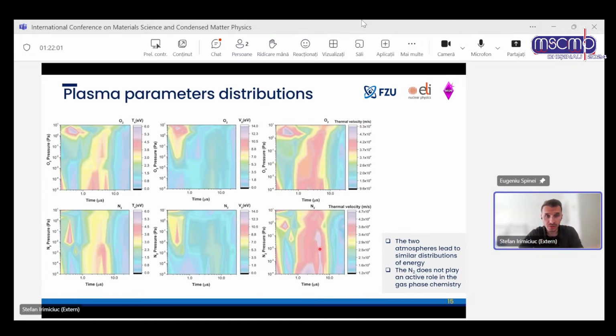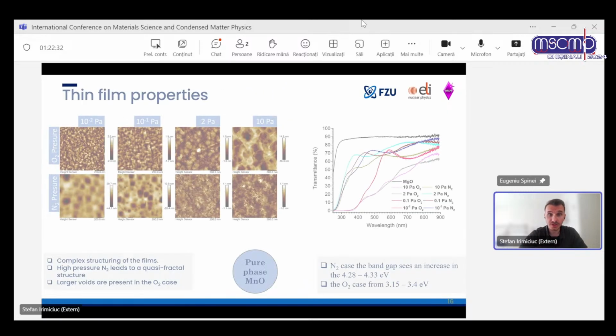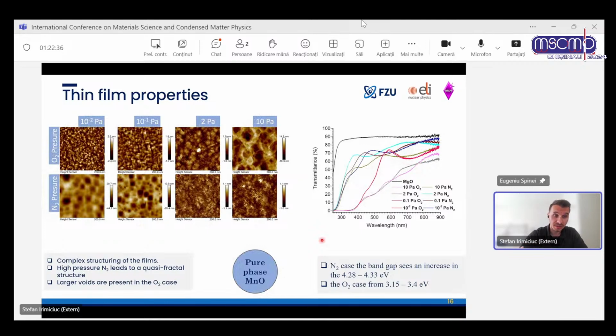And then we can also look at the more delicate plasma parameters like electron temperature, plasma potential, and thermal velocity. I would like to point out that the values and the distributions look quite similar. So when we try to deposit manganese oxide in oxygen or in nitrogen, the plasma parameters are similar. This is a signal that we need to pay attention to, because when we deposited the films, we actually found out that nitrogen doesn't go into the structure of the film, but we can produce pure phase MnO. This was a signal from the plasma. The plasma told us that it's the same, but then we can get really nice crystalline and well-oriented films.